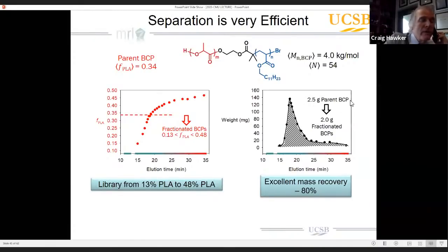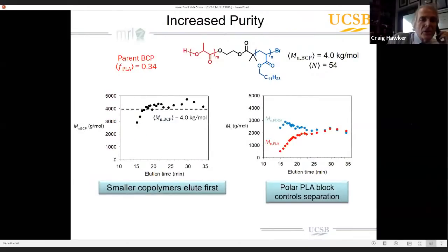We start with 2.5 grams of the parent block copolymer, and we obtain 2 grams of fractionated block copolymers, as well as the other couple of 100 milligrams, which tends to turn out to be unwanted homopolymer contamination. And so from one sample, we now have materials with a broad range of levels of lactide incorporation.